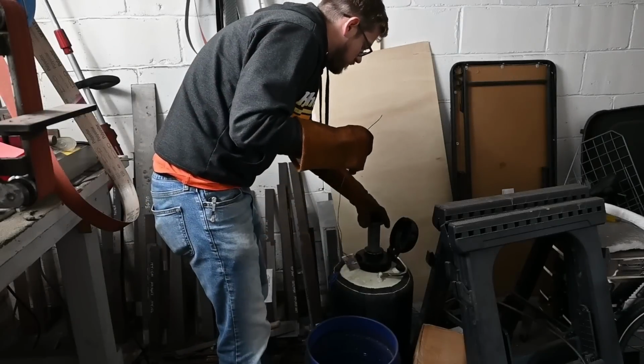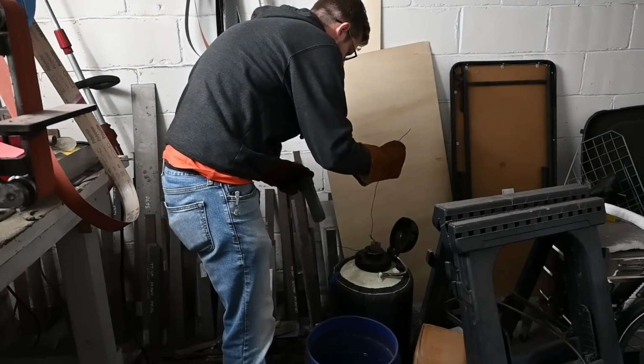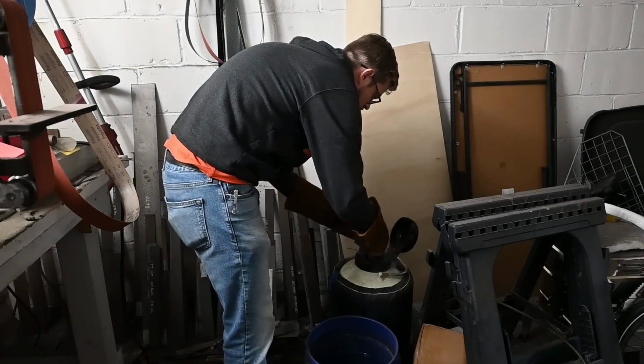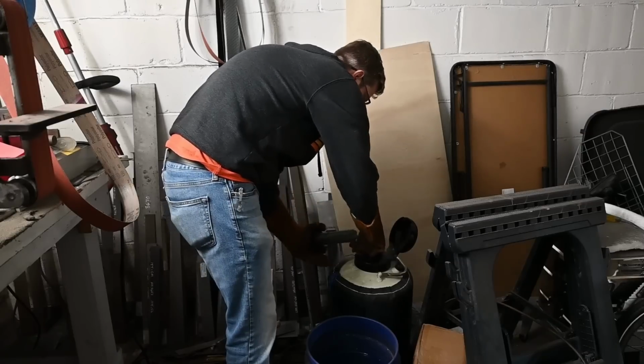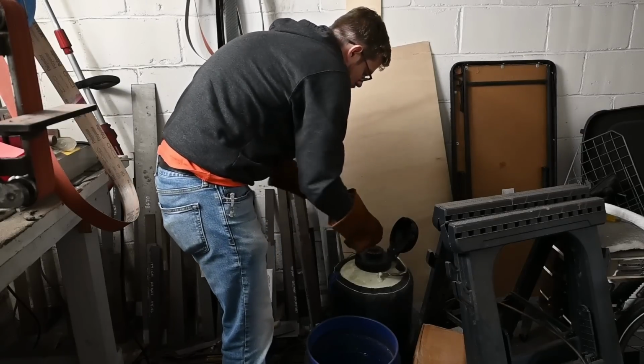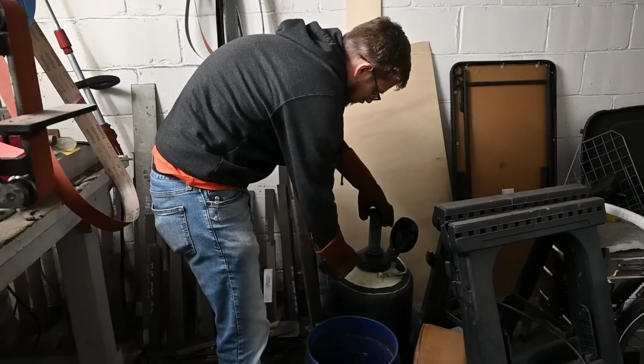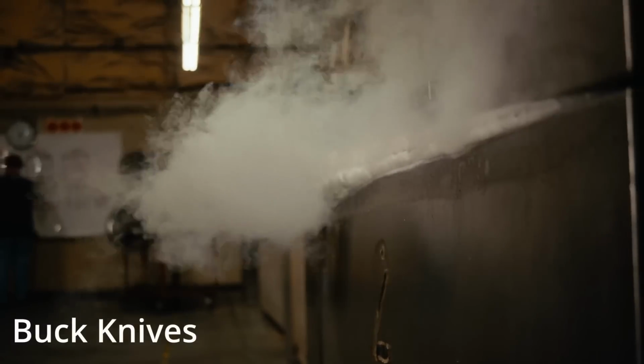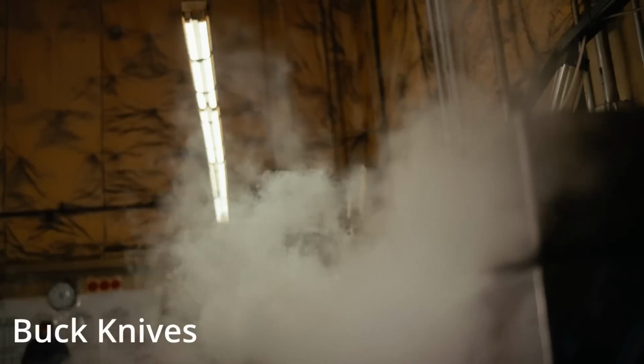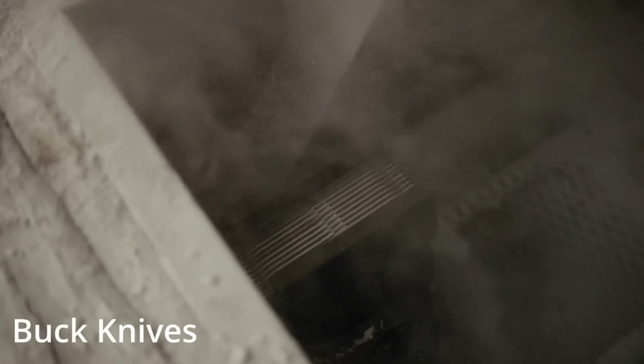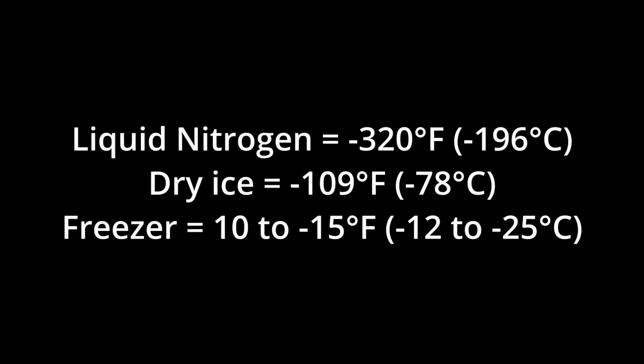In terms of cold or cryogenic processing, there's various equipment that can do that. The simplest is just to use liquid nitrogen in a dewar, and you can dip the knife directly into that. There are fancier setups that will spray liquid nitrogen or cool down a refrigeration unit with liquid nitrogen. There are also refrigeration units that don't use liquid nitrogen, and they can get quite cold, though not as cold as liquid nitrogen. Liquid nitrogen is about negative 320 Fahrenheit, negative 196 Celsius. Dry ice is also relatively common for sub-zero temperatures. It's about negative 109 Fahrenheit or negative 78 Celsius.